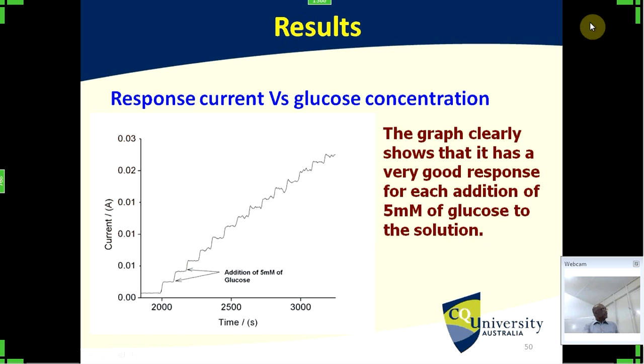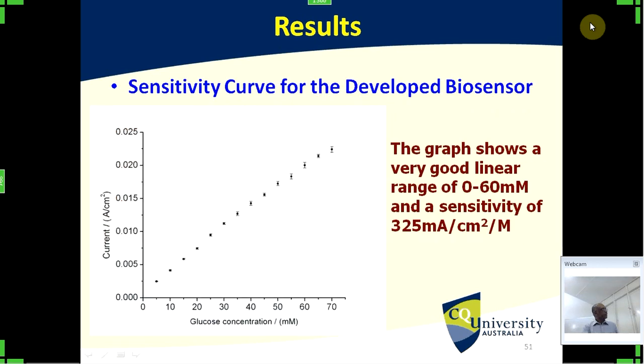And this is the response curve we got from that one. And again, the same thing with the standard one. And we got 325 milliamperes per centimeter squared per mole. It's a huge improvement in the sensitivity without using any templates, so you can use any.